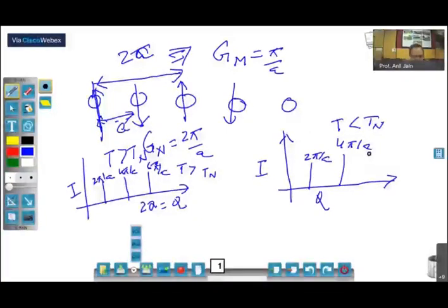But here you know that your magnetic reciprocal lattice vectors are different from the nuclear reciprocal lattice vectors. So you will get this additional peak, let's say pi/a, 3pi/a. So as a thumb rule, when you have antiferromagnetic kind of ordering, you get additional reflections in your neutron diffraction pattern at low temperature. Then the idea is to get the information about the magnetic structure of your sample.